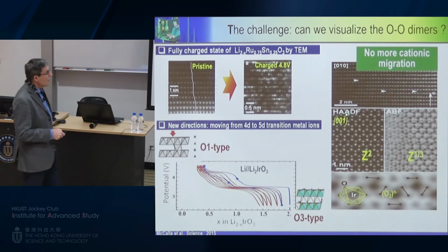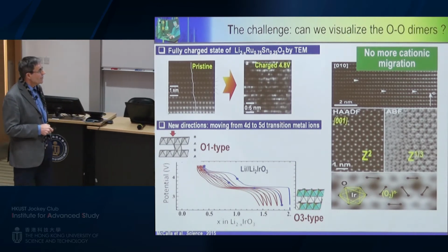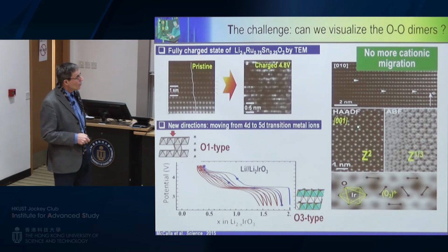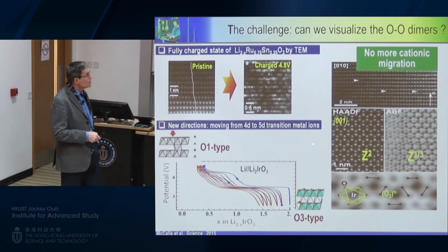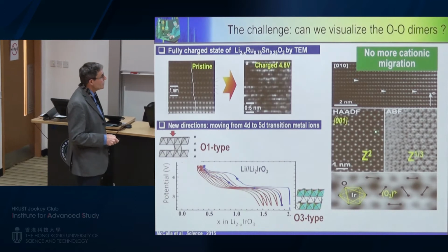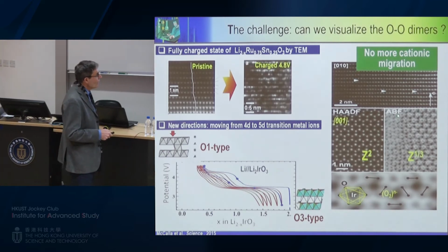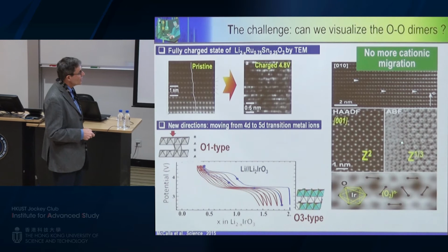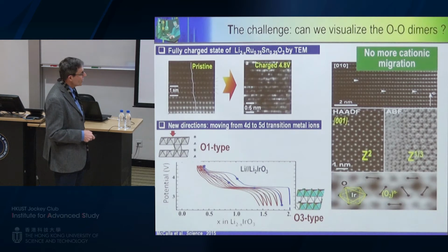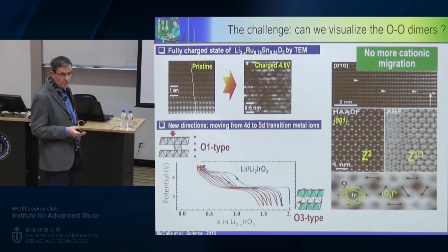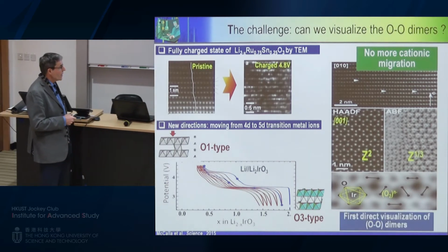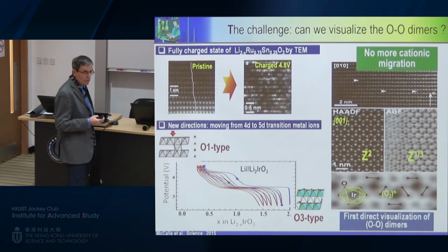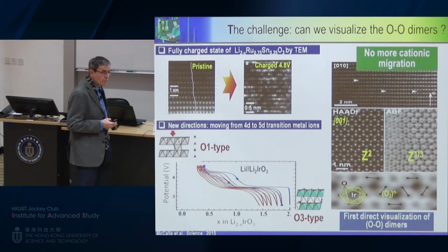Then, when you look at the high angular dark field image, we nicely see the honeycomb associated to these iridium atoms. And then, when you go to the annular bright field image, in this case, you can see the nice contrast, and you can distinguish this kind of distorted IrO6 octahedron and this kind of dimer corresponding to this peroxo species. And this was directly the first direct observation of these oxygen-oxygen dimers.